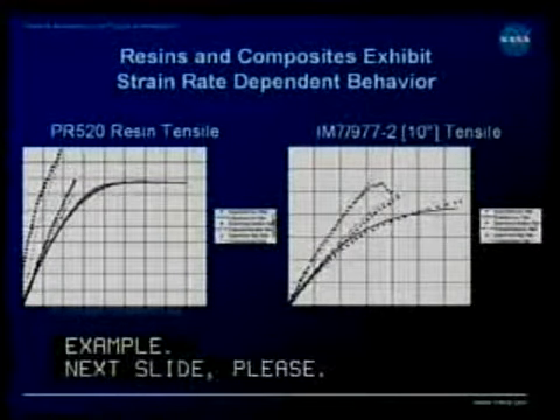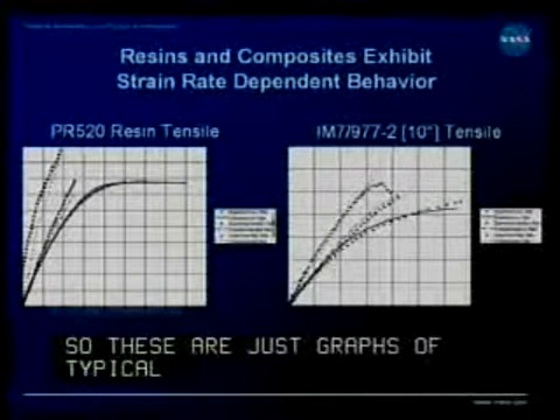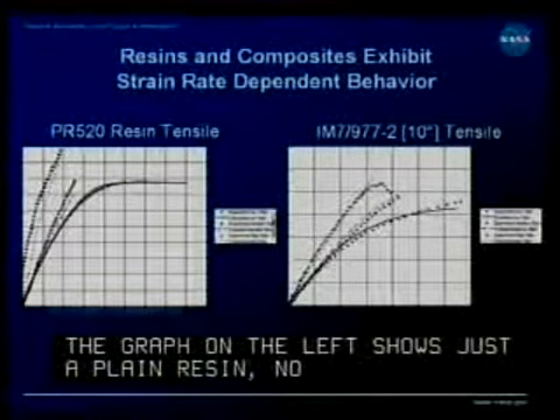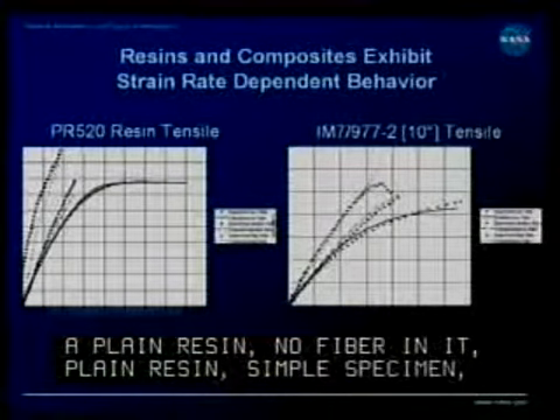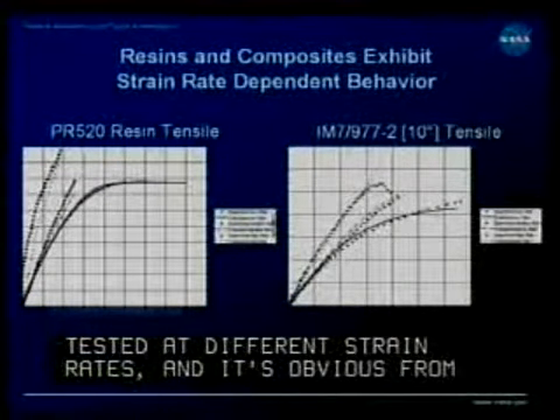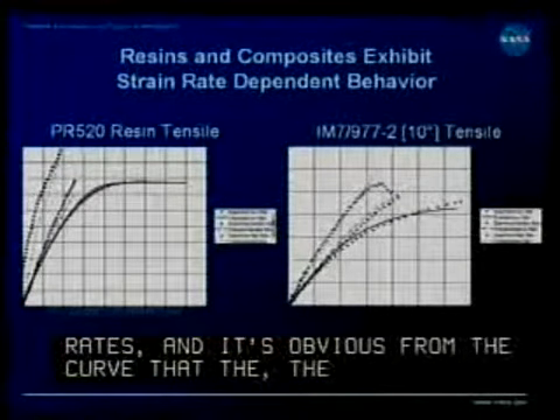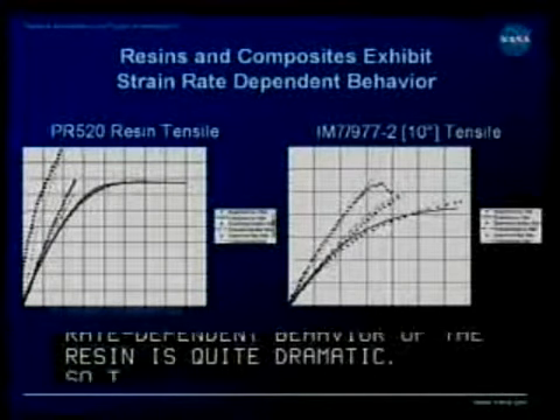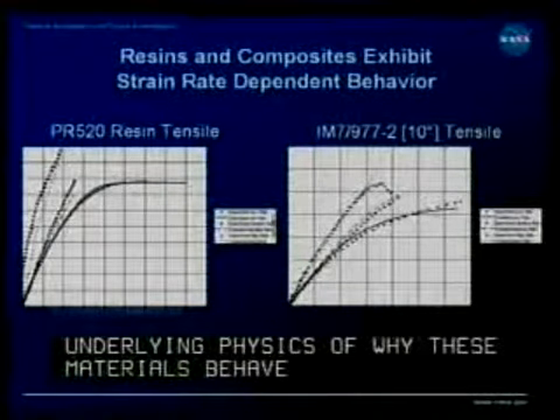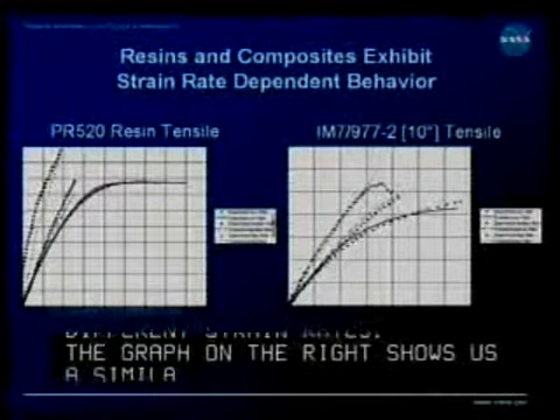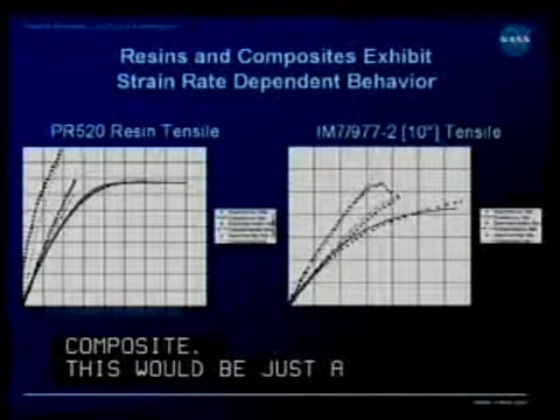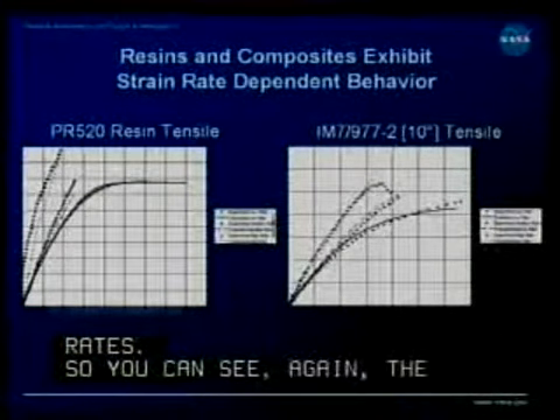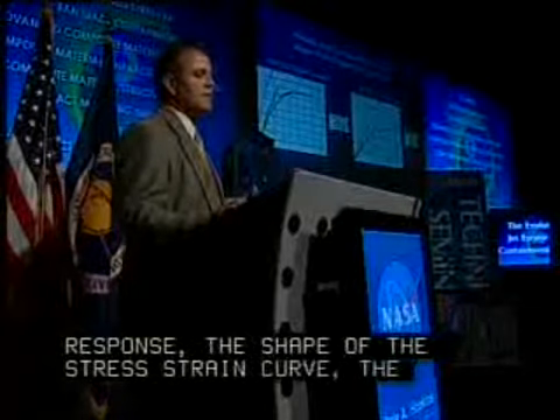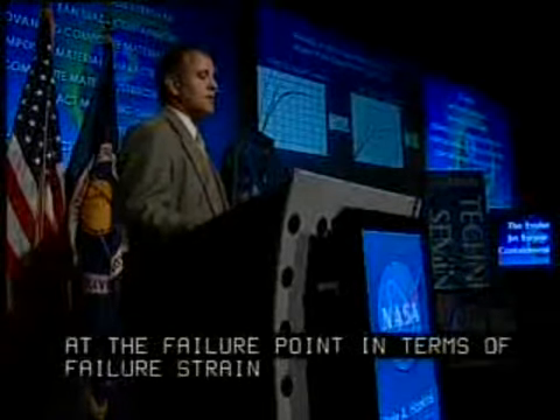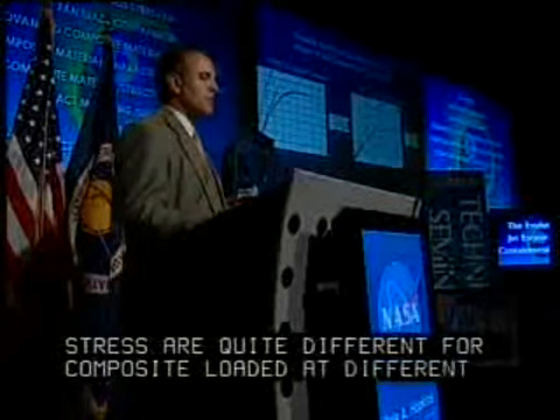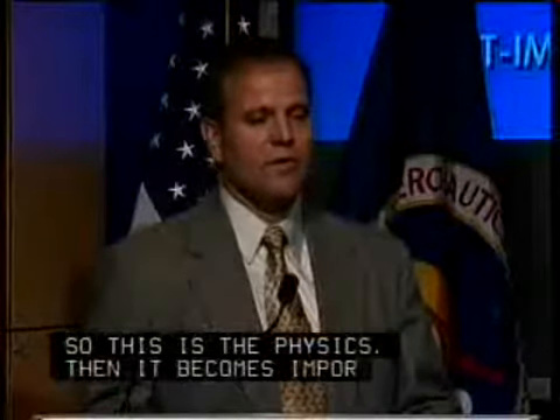So these are just graphs of typical tests. The graph on the left shows just a plain resin, no fiber in it, a simple specimen, tested at different strain rates. And it's obvious from the curve that the strain rate dependent behavior of the resin is quite dramatic. So this is part of the underlying physics of why these materials behave differently at different strain rates. The graph on the right shows a similar result for a simple composite. This would be just a unidirectional composite that's tested at different strain rates. So you can see, again, the shape of the stress-strain curve and the values at the failure point in terms of failure strain and failure stress are quite different for a composite loaded at different strain rates. So this is the physics that becomes important to try to incorporate into new modeling tools. Next slide, please.